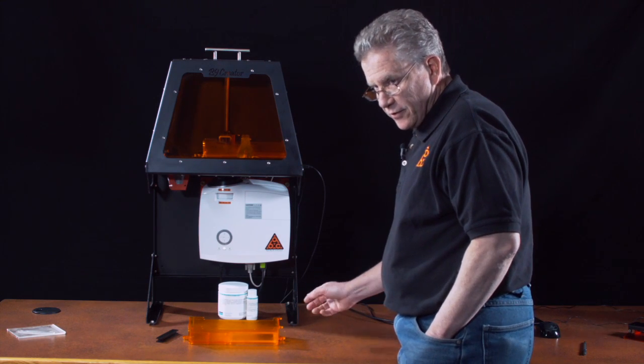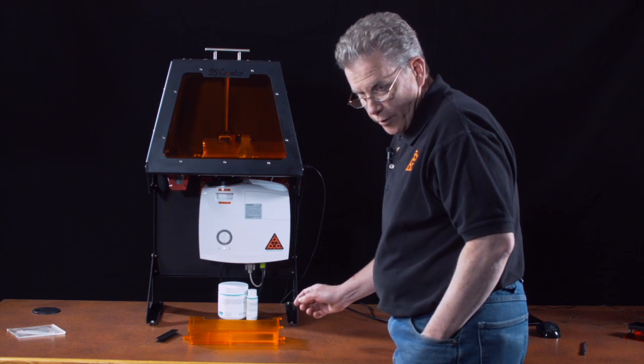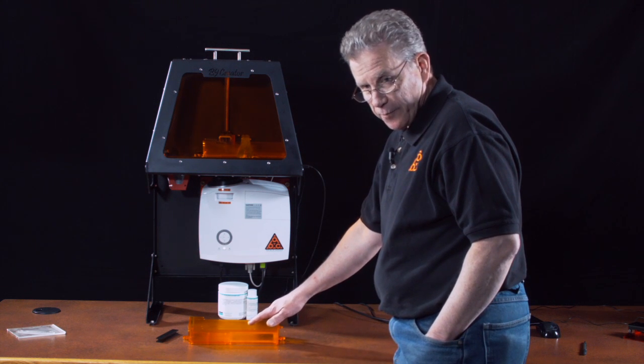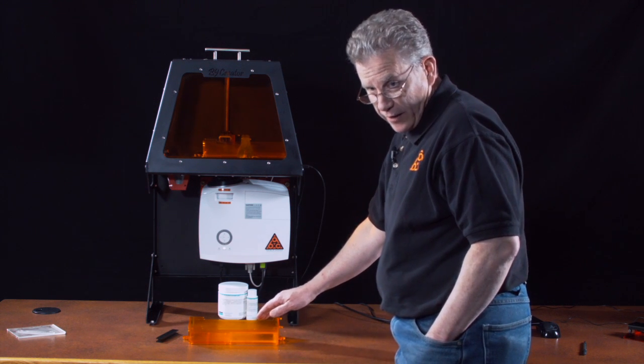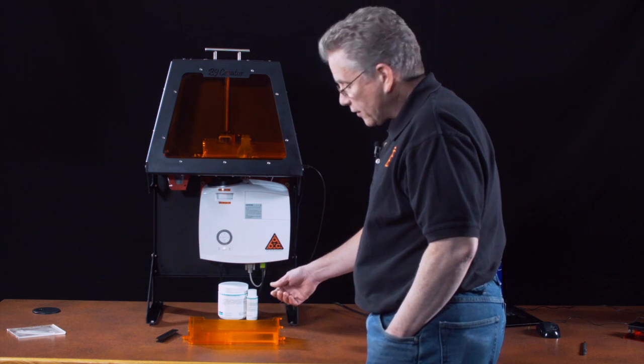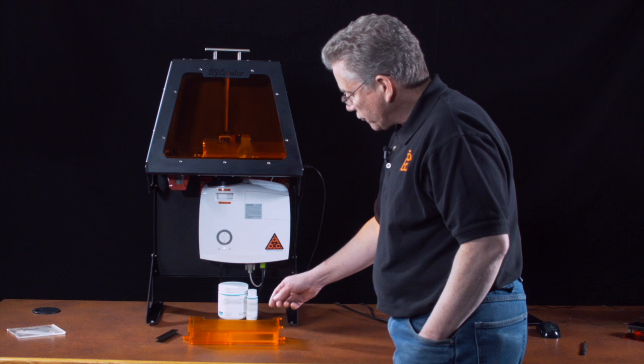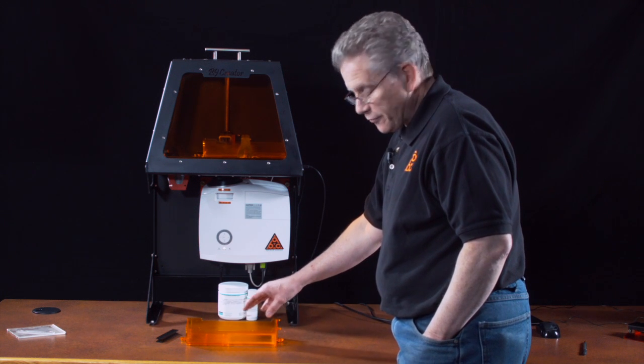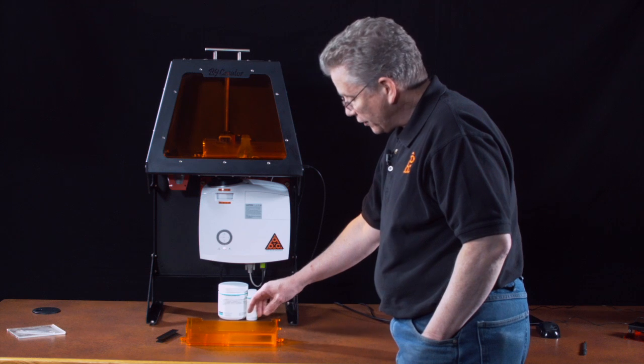Now, if you have an environment that's 74 degrees or warmer, it'll take about 48 hours for that PDMS to cure. It can take longer than that if your environment is colder. Humidity can also affect that time duration. But the important thing is to let it sit there for about 48 hours until it's completely cured.